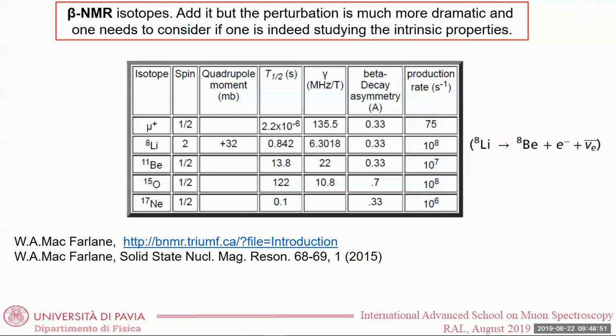The NMR signal scales with about the square of the magnetic field. If you're doing a high field experiment, you have a huge signal and a few acquisitions are enough. If you're doing low field, you have a much poorer signal to noise ratio. So it's not easy to compare, but in general MUSR is a bit faster, and you can reasonably do a set of experiments on a system in a few days, while NMR will require more time. But this is very general.